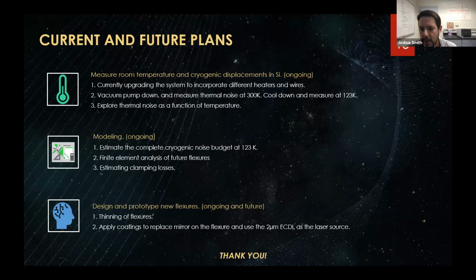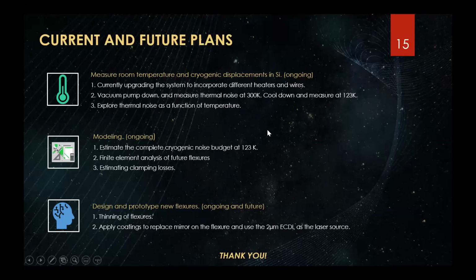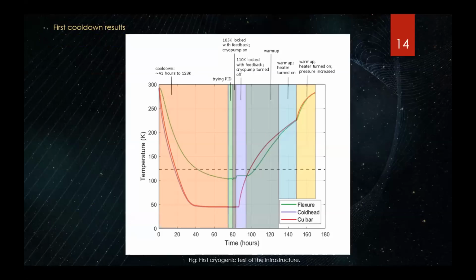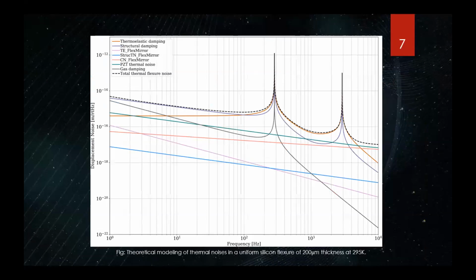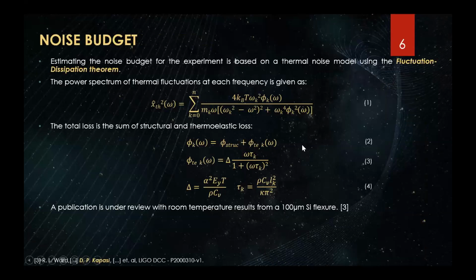The first question is from Julie, who asks, how was the frequency dependent loss estimated? The frequency dependent loss is the thermoelastic loss for us in this case. We used this loss over here to estimate the thermoelastic loss, and then put it back into this power spectrum to calculate the frequency dependent loss. The structural loss is frequency independent, so that just comes from the ring down measurement of your cantilever.